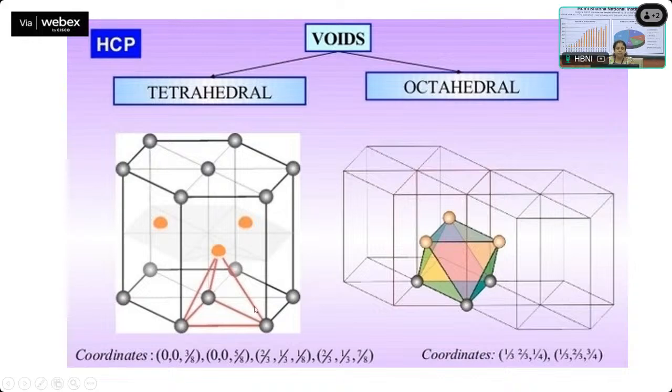All right, so let's restart it. Let us concentrate on the tetrahedral hole that is being shown here. The coordinate for this particular lattice point was 2/3, 1/3, 1/2. Now the tetrahedral void. By the mathematical definition, the centroid of a tetrahedron, if I draw a vertical line from the vertex to the base, lies at 1/4 of it.